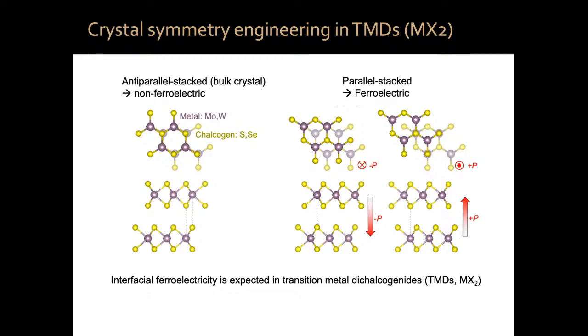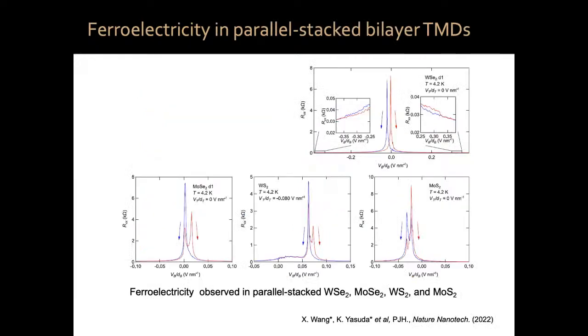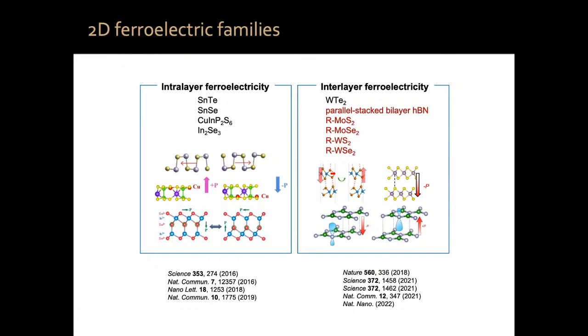And we can parallel stack them on top of each other. This leads to different opposite electric dipole moments. And we have made twisted structures of all of these materials, WSe2, MoS2, WS2, MoSe2. So all of them become ferroelectrics, okay? So in a process of about a year, we have doubled the number of two-dimensional ferroelectric materials which are known, okay? And not only that, with the same trick, you can engineer ferroelectricity into any material as long as it